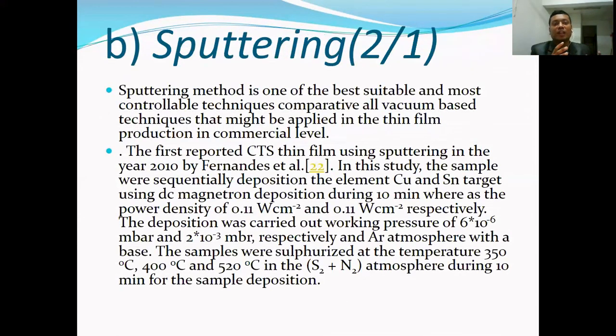And secondly, we use sputtering. Sputtering is the most important technique. The sputtering method is one of the most suitable and controllable technologies, comparable to all vacuum-based technologies that might be applied in thin film production at a commercial level. The first reported CTS thin film using sputtering was in the year 2010 by Fernandes. In this study, the samples were sequentially deposited from copper and tin targets using DC magnetron deposition for 10 minutes, with power densities of 0.1 watt per centimeter squared respectively.